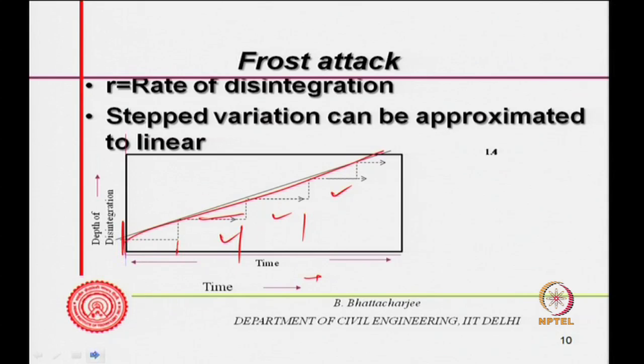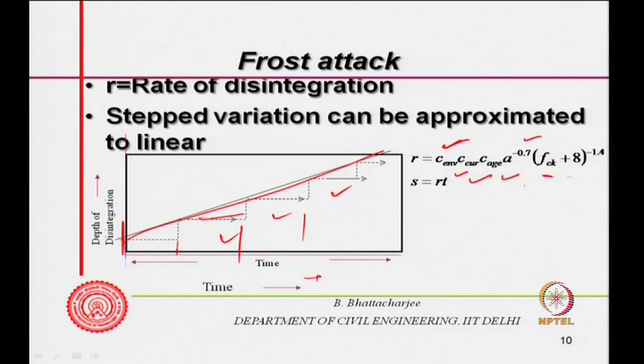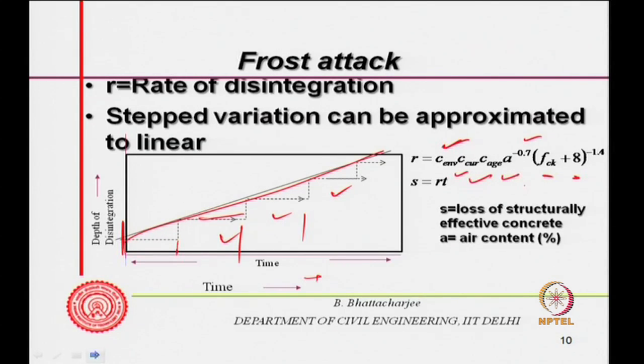The slope of this line would be the rate. So, rate is given by another empirical formula, with coefficients called C environmental, C_env, C_cur, and C_age, multiplied by a, the air content, to the power minus 0.7, and (f_ck + 8) to the power minus 1.4. Now, S is the loss of structurally effective concrete, a function of rate times time. So, the loss of structurally effective concrete is given by this, which is the slope of